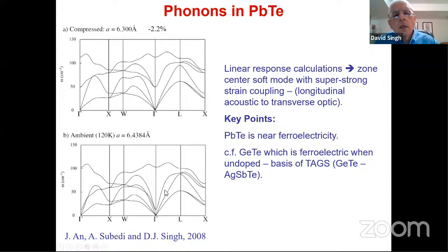And then there's some other low frequency vibrations, and they are caused by the fact that lead telluride, it's not ferroelectric, but it's near ferroelectricity. So this was all known. So although we did calculations, it was already known. So there was nothing new that came directly from this calculation that we reported. But what was new is that when you do calculations, you can easily change the pressure or the volume of a material. And so if we compress lead telluride, then we got something very different. And so what we got was this longitudinal branch and this transverse branch. You saw those already. Those are the same, more or less.